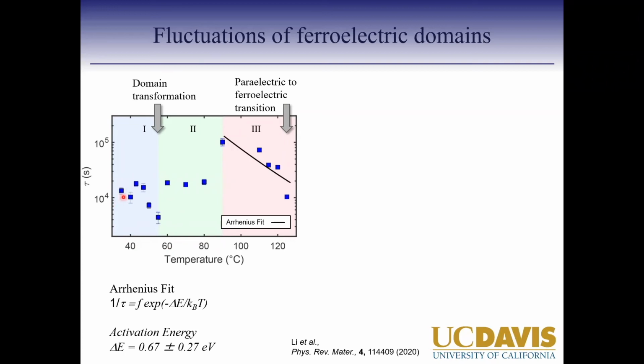So when we start at room temperature, we still see that these domains are fluctuating. But as we get to the domain transformation temperature, where from AB domains you switch to AC domains, the fluctuations are fastest. And so the time scale drops down. And once the AC domains form, then the fluctuations start to slow down again. And then at 90 degrees or so at these higher temperatures, they are perfectly stable. And then as you get to the Curie temperature, where even the AC domains are going to disappear, your material is now going to transform into cubic phase, and the fluctuations get faster in the material.